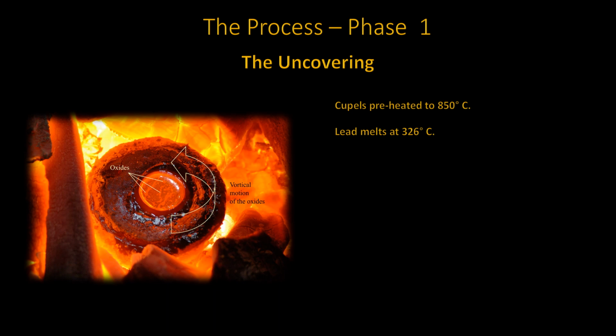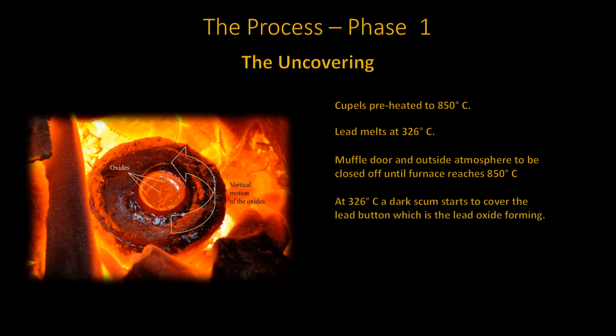Elemental lead melts at 326 degrees centigrade. Preheating reduces the melting time and reduces the possibility of spitting. The muffle door must be kept closed and any air inlet into the chamber must be sealed off. At about 326 degrees centigrade, a dark scum will start to form on top of the melt and eventually fully cover the molten lead. This is the lead oxide that is forming and will soon disappear in about 1 to 2 minutes, and the melt will become bright.